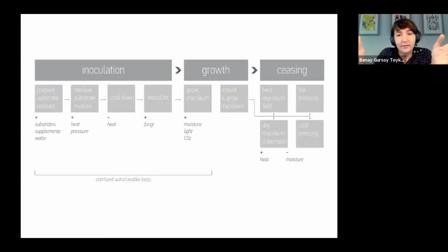So this is the basic mycelium-based growth chart. It starts with inoculation, and then you first prepare the substrate, mix it, sterilize the substrate, let it cool down, and then inoculate with fungi. For this project, we used sawdust and straw, and then inoculated with the locally abundant oyster mushroom species. Even now, in Pennsylvania, it's a very abundant species. Our yard is now infested, I would say, with oyster mushrooms.